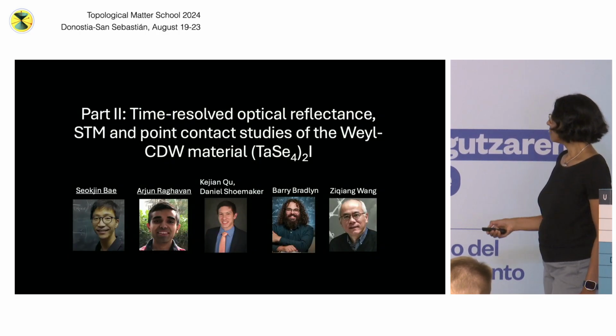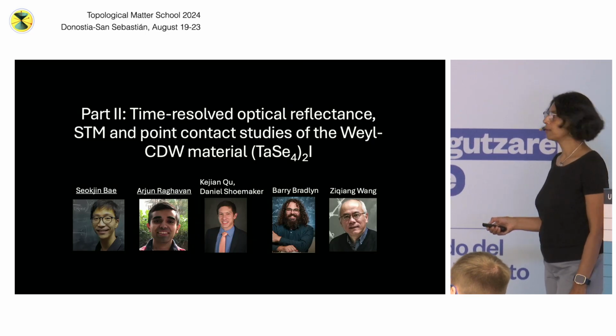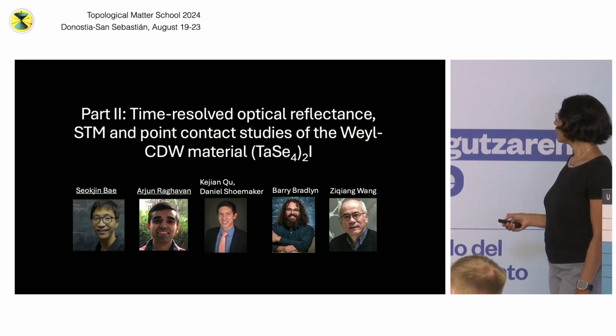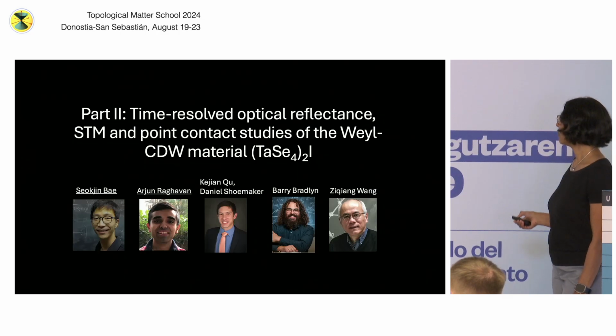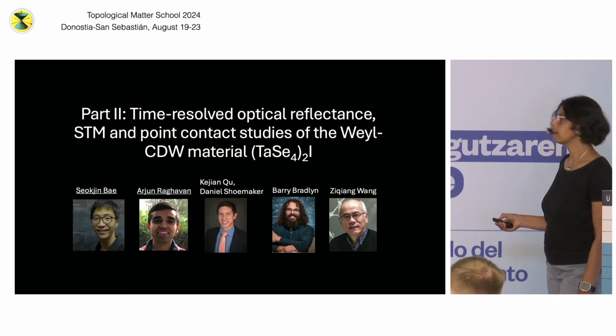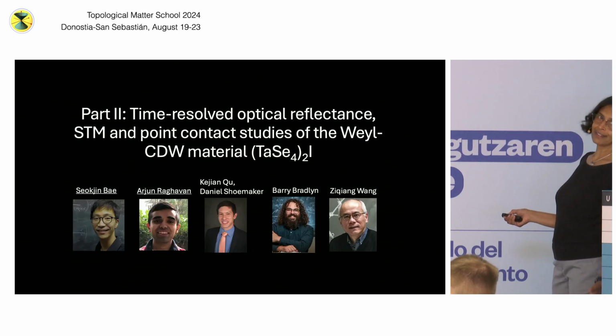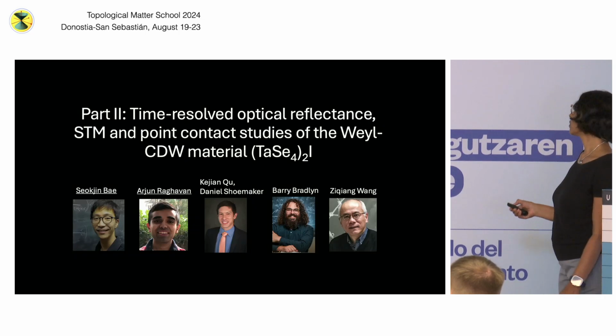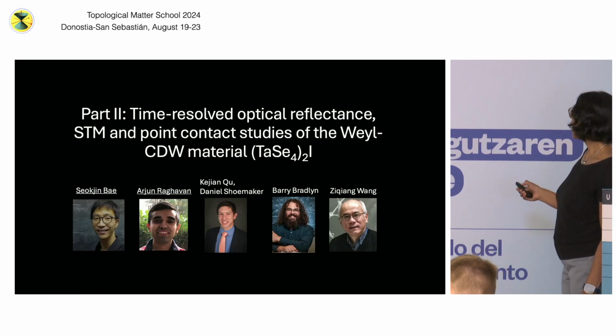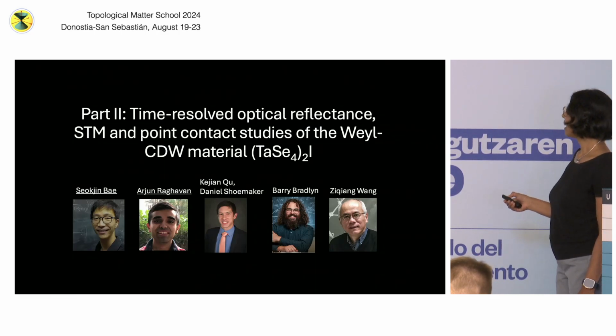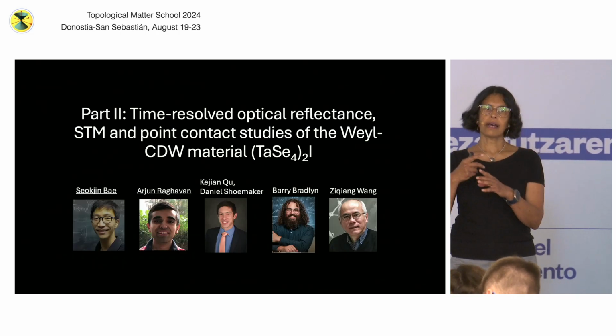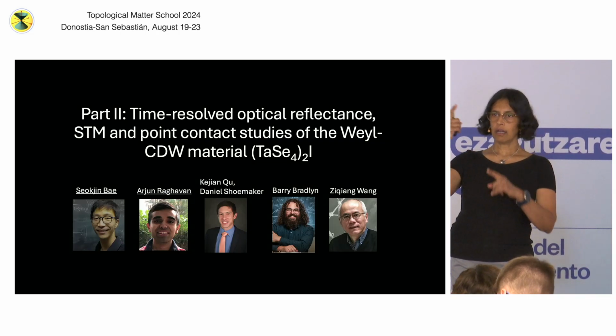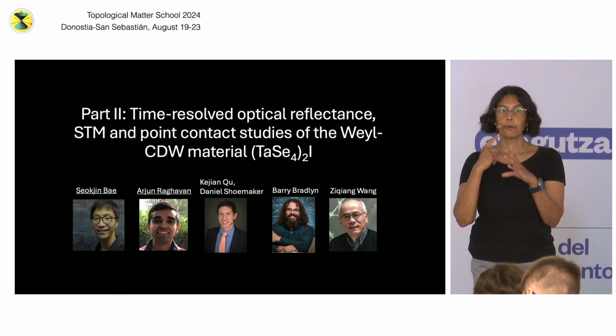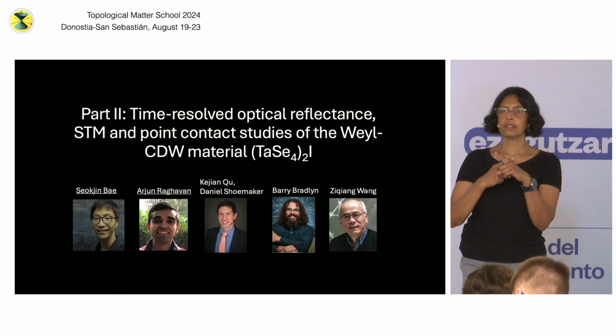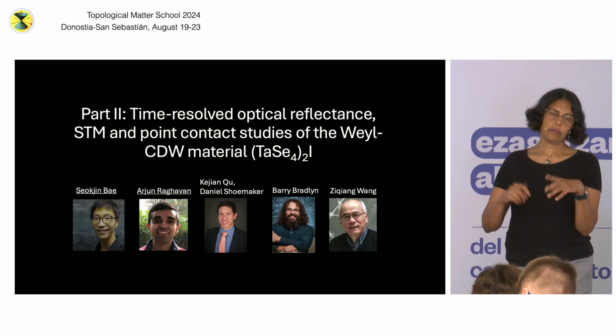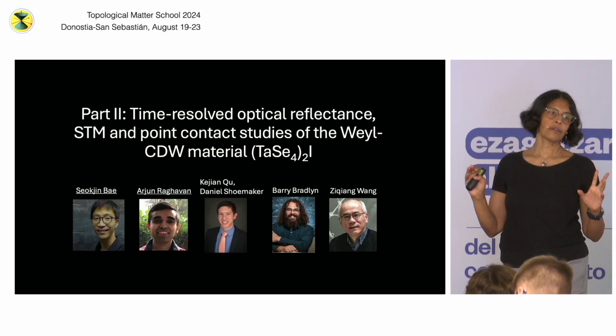Again, these marvelous people, Sokjin and Arjun, built this beautiful instrument and got this amazing data. We got samples from Daniel Shoemaker's group, and we're working with Barry and Ziqiang for theory support to help us understand what's going on. We don't fully understand what's going on in the system. It's a wild charge density wave material, tantalum selenium iodide. Above the CDW transition, it's a Weyl system. It has broken inversion symmetry, and that's why you have these Weyl cones instead of Dirac cones. So the system has very little symmetry, just to start with.